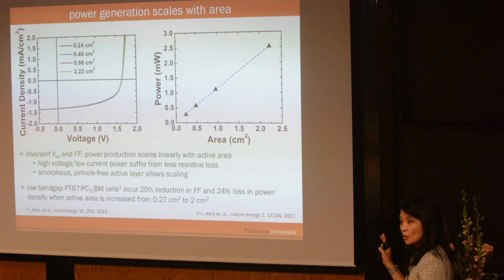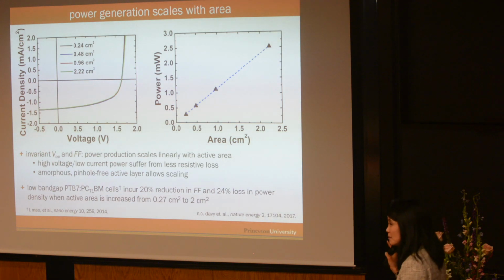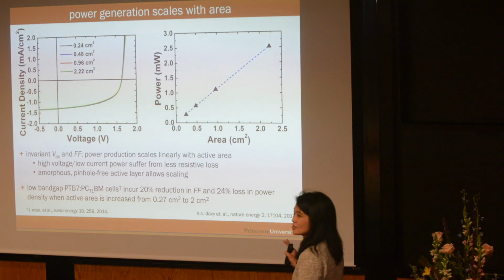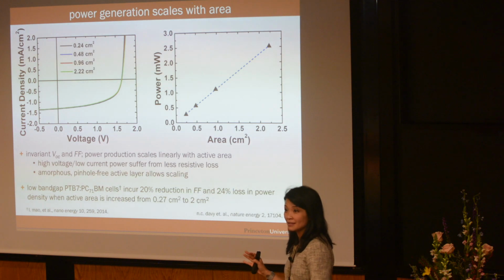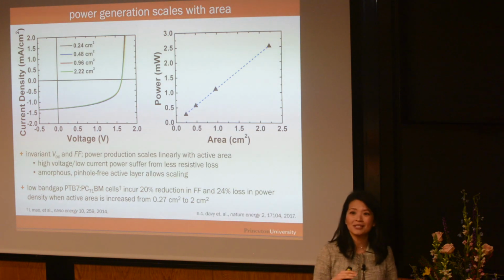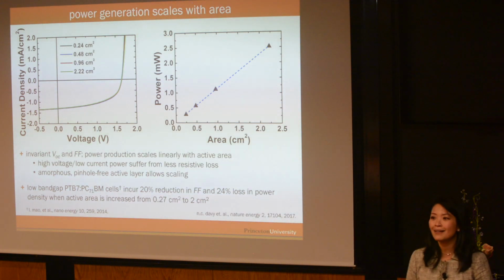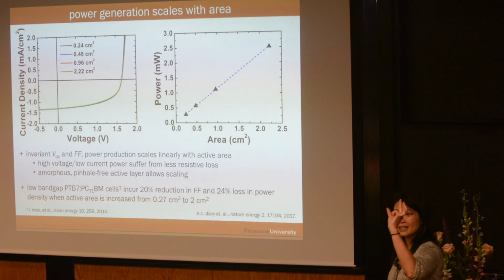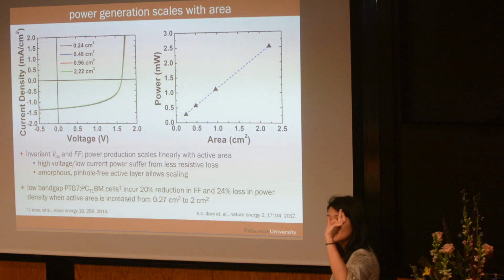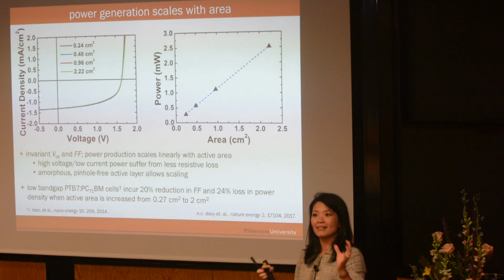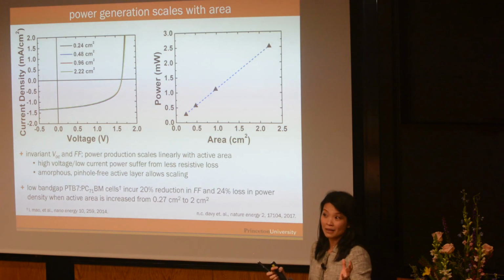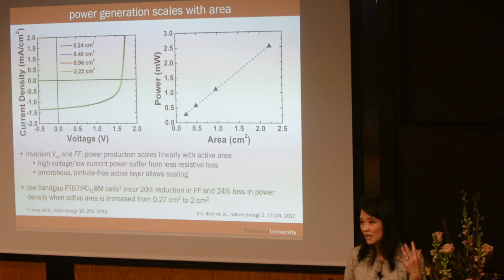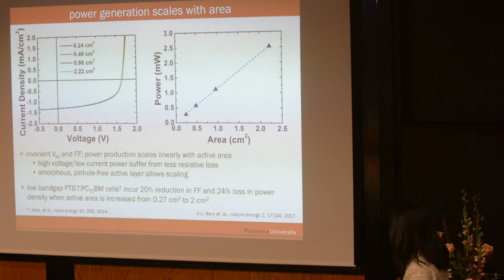This is where the amorphous layer becomes important. Remember, we're targeting window applications, so we need to make large area cells. And for those of you who make solar cells, you know that the typical cell that you make in your lab is about yay big, right? 0.1, 0.2 centimeters squared. And then when you scale up, you run into trouble because you have pinholes, et cetera, that then short through, and you can't make those cells work over large areas.